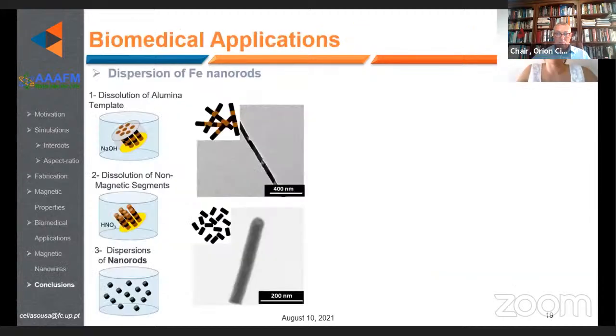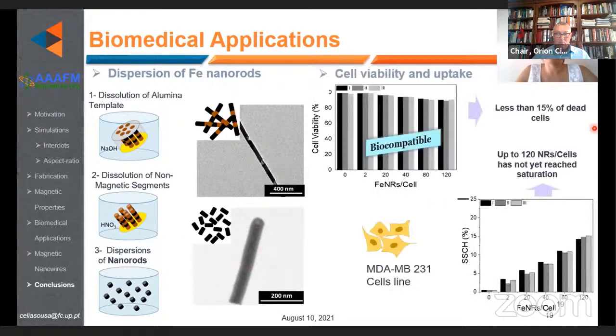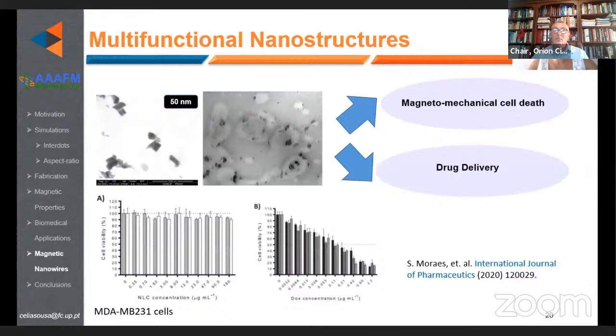To evaluate the possibility to use these nanowires for biomedical applications, we performed the dispersion of iron nanowires in a solution. First, we removed the alumina membrane, then we removed the copper layer by selective etching, obtaining a suspension of iron nanowires. These nanowires showed a biocompatible behavior with less than 15% of cell death, and we are also able to uptake up to 120 nanowires per cell.